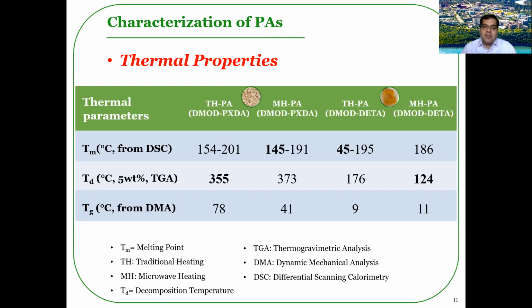As you can see in this table, the semi-aromatic polyamides are generally more thermally stable than the linear polyamides. All the polyamides had a melting point of more than 145 degrees centigrade, except the traditional polycondensed linear polyamide with the first melting point of 45 degrees centigrade. Although the semi-aromatic polyamides started to decompose at a temperature as high as 355 degrees centigrade, the linear polyamides couldn't tolerate more than 124 degrees centigrade.